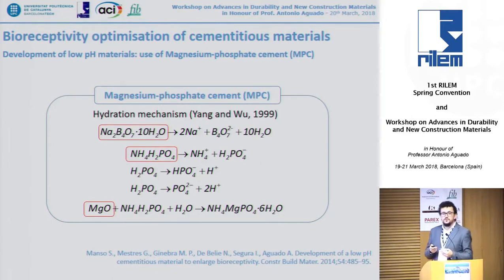Our first attempt was to reduce the pH of cement. We tried to use different admixtures or different cements, but the fact is that the normal pH of cement, which is around 13, is very difficult to reduce to a level that can allow us to have biological colonization in real time. So what we decided was to use magnesium phosphate cements, which are materials that are actually being used for dental implants, that are biocompatible and have a pH that is close to 7.